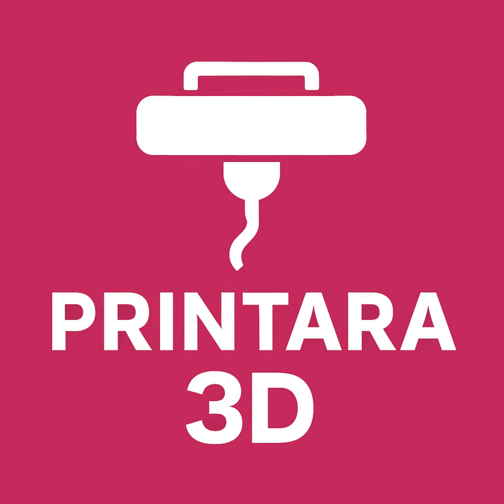Precisely. The melt pool dynamics are totally different. And that brings us to the other critical adjustment, which is retraction. Right. Retraction is when the printer pulls the filament back slightly to relieve nozzle pressure, preventing stringing, when the print head moves across empty space. Yeah, with rigid materials like PETG, you might retract several millimeters. But with TPU, retraction must drop to an absolute minimum of 0.5 to 1 millimeter. Because if you pull a highly flexible rubber band backward from one end, it just stretches. It does not actually pull the material up and away from the nozzle opening. It just thins out inside the melt zone? Yes, and the consequences of deep retractions on flexible materials are catastrophic.